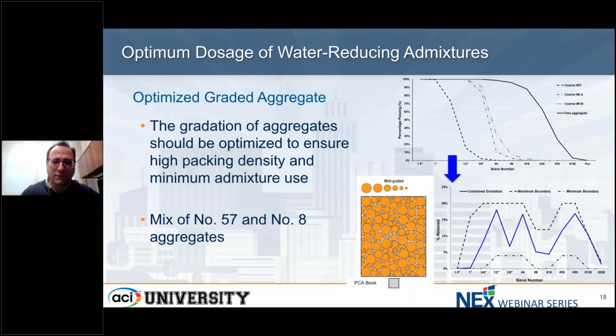So as I mentioned, we have to optimize our aggregate system for this purpose. To do that, in our experiment, we use basically number 57 aggregate, number 8, as well as our sand. As a preliminary approach, we use this triangular curve, which gives us the combined gradation for concrete aggregate. And we want to stay in these boundaries. You have to make sure you are staying within that boundary. So we change the proportion of these three different sizes of aggregate to make sure we stay in that range. And this is an example I am showing here. Again, the purpose here is to improve the packing density and reduce the void content, so we need less cement paste to fill those voids.